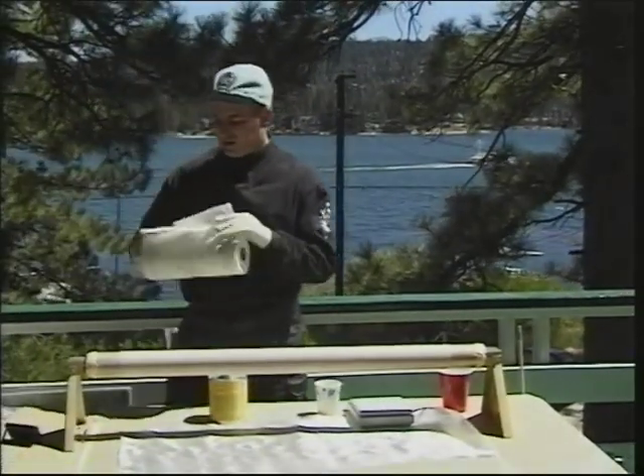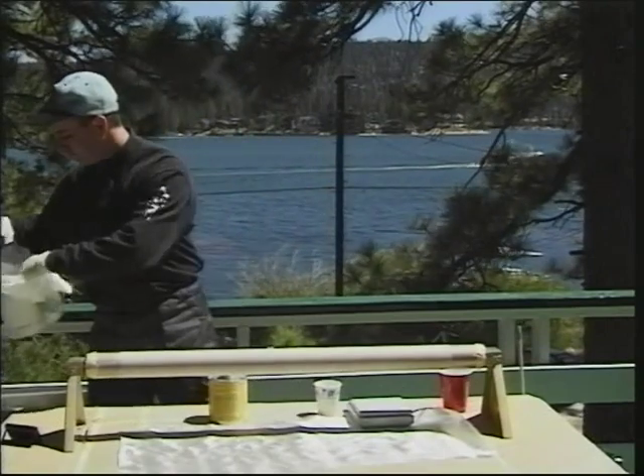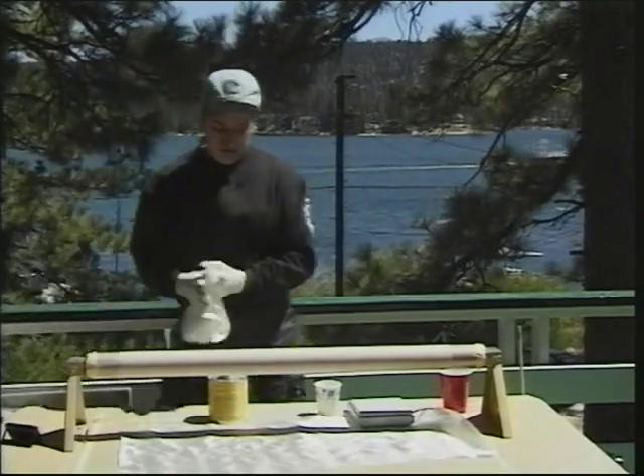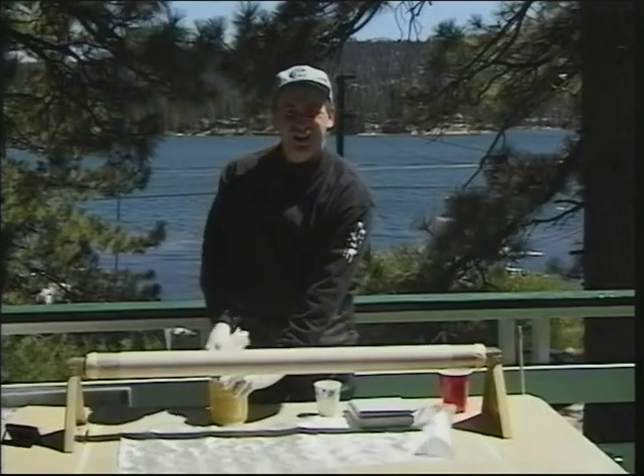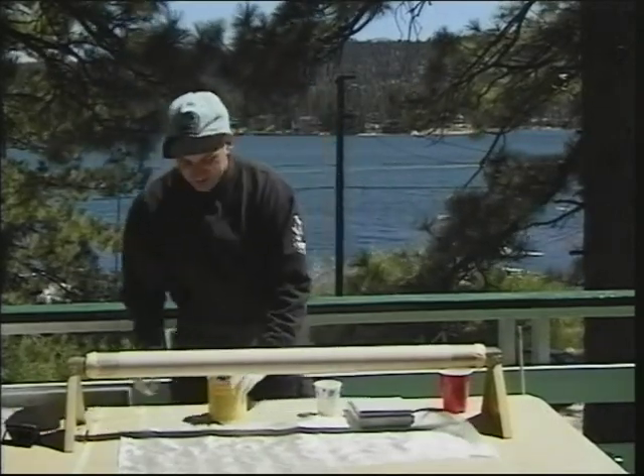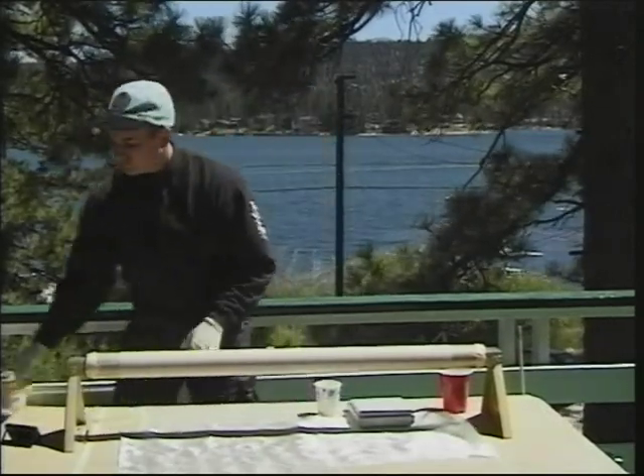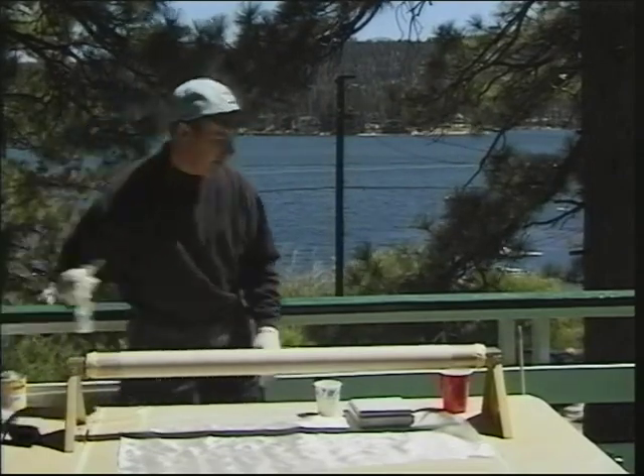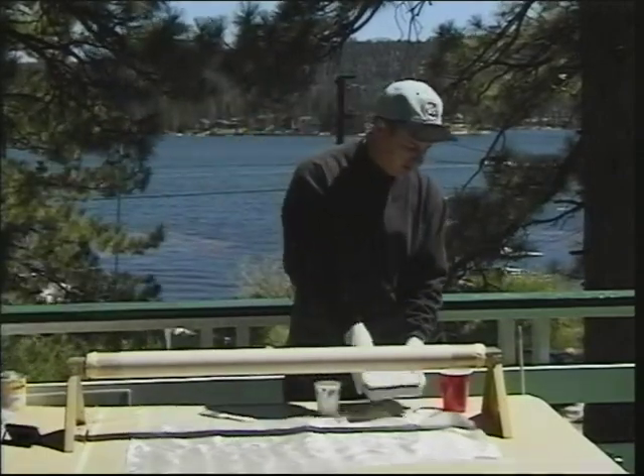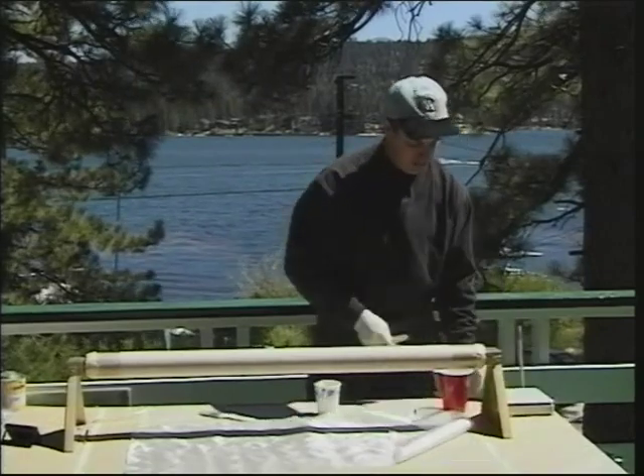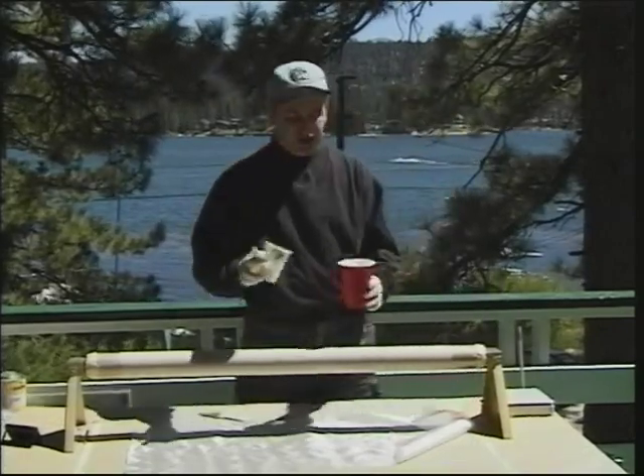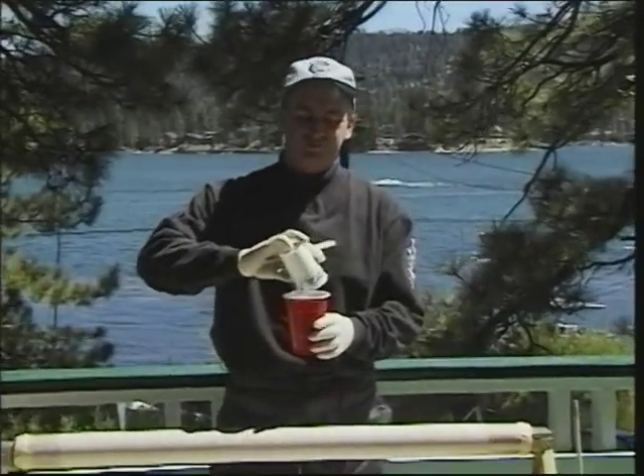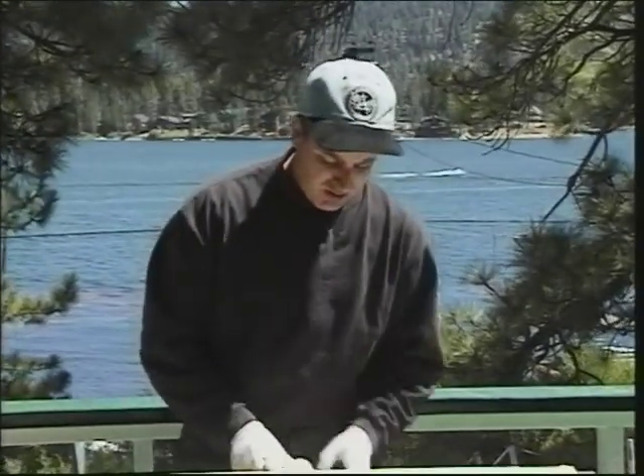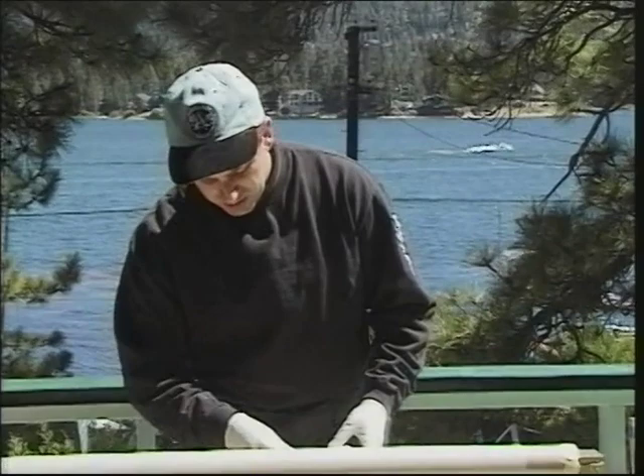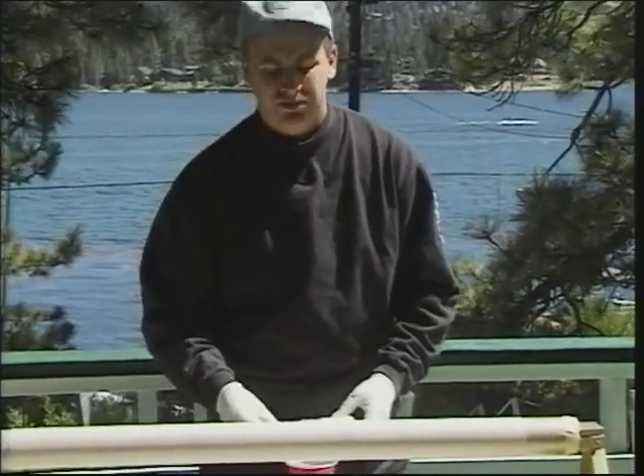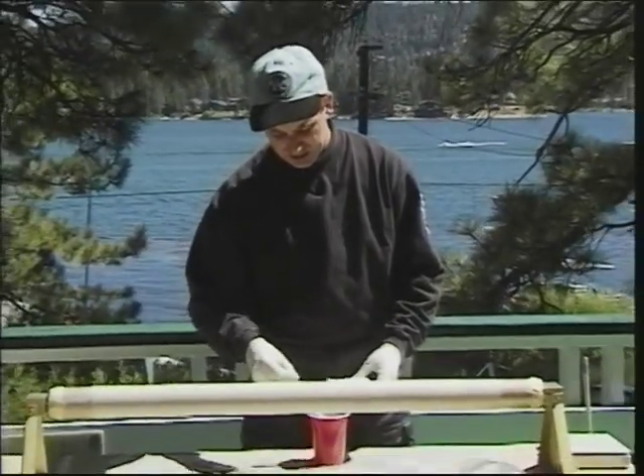Same thing applies with the hardener as far as keeping it clean. It's good to have a little roll of paper towels handy while you're doing all this stuff. If you get any drips, you can clean it up real easy. To mix the resin now that we've got it proportioned, you just add the hardener to the resin. Be sure to scrape out any hardener in there so you get an accurate proportion. You don't want a gram of hardener left in your cup.